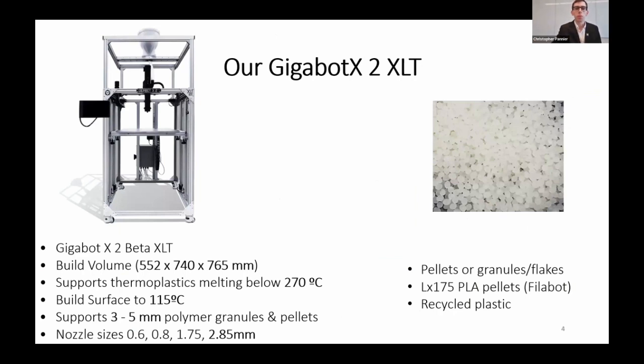So we received a Gigabot X2 XLT, one of the extra large and tall models. And we were in the beta group of receivers. So we have a Gigabot X2 beta XLT. The build volume on this machine is more than half a meter on the shortest axis, right? Three quarters of a meter, just about, on length and height. So for a lot of 3D printers, you think of these as the overall printer dimension, but that's the build volume on this machine. And it's got an extruder that takes in pellets or granules, a form that looks like this, 3 to 5 millimeter size, and extrudes them into the bead of the 3D printed part.